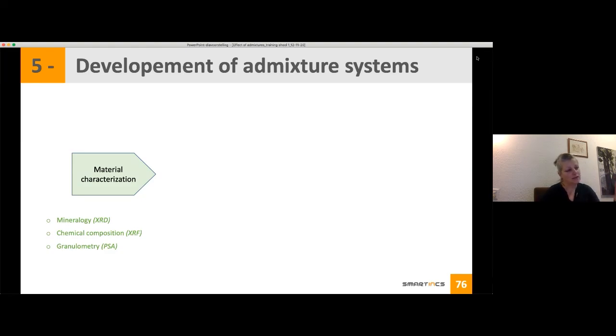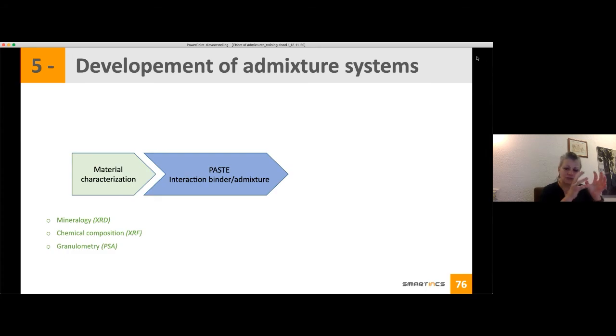And when you have this information, then we look at the interaction, how my superplast is going to interact with my binder or with my cement. For this, we use two different methods. The first is the mini slump test, where you can see the influence of the dosage on the workability.